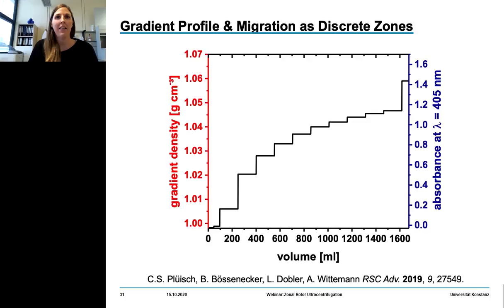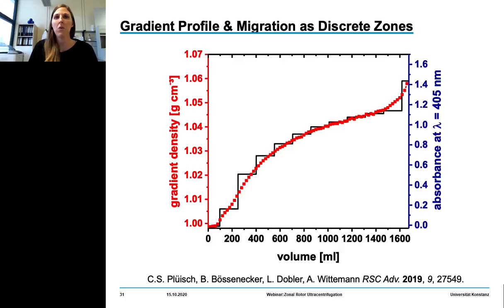Let's have a closer look. We are building a step gradient in this example; however, the density steps even out during centrifugation and the profile converts into a continuous one. Here we are using a convex gradient because this gradient profile shape is believed to provide particularly good separations.